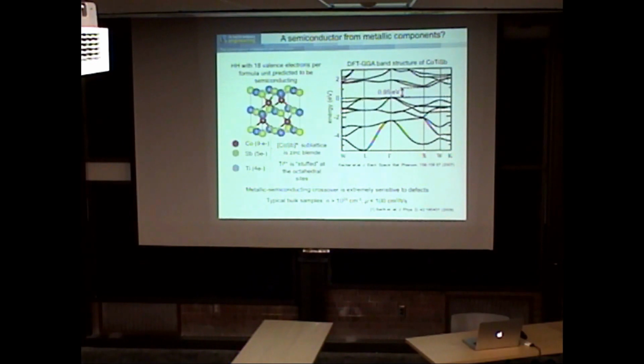Okay, so cobalt titanium antimony has a lattice parameter of 5.888 angstroms, very close to indium phosphide. So in principle we should be able to grow this on indium phosphide. And this is the band structure. Again, pointing out that at X is where your electron pocket is for the conduction band. Here's the valence band. And bulk samples tend to have high carrier concentration.